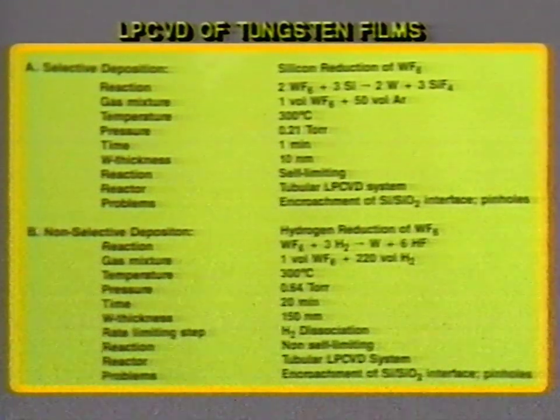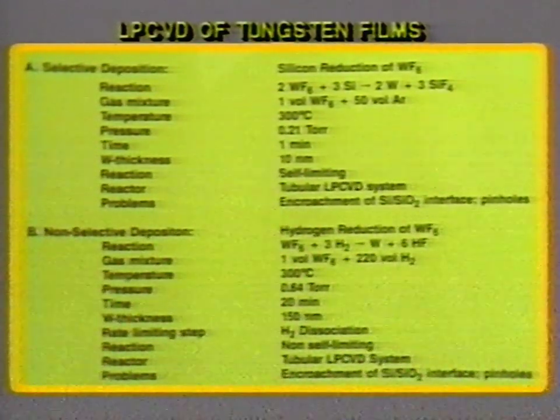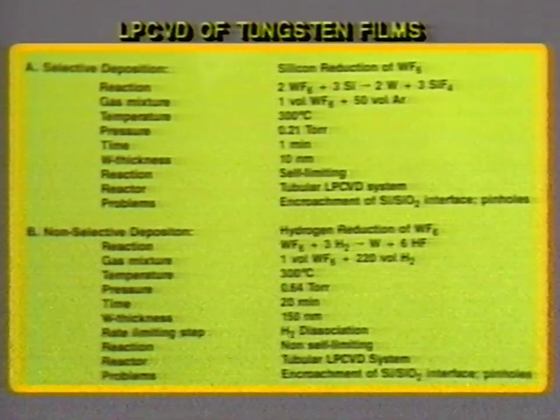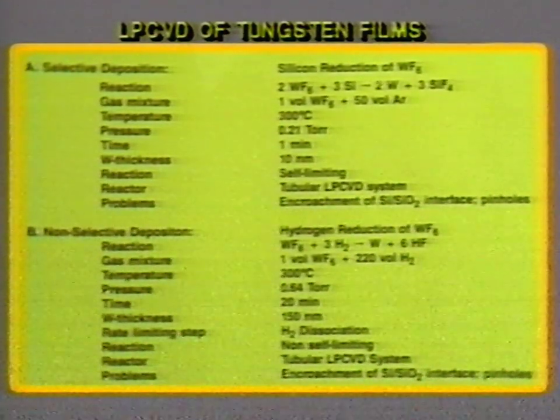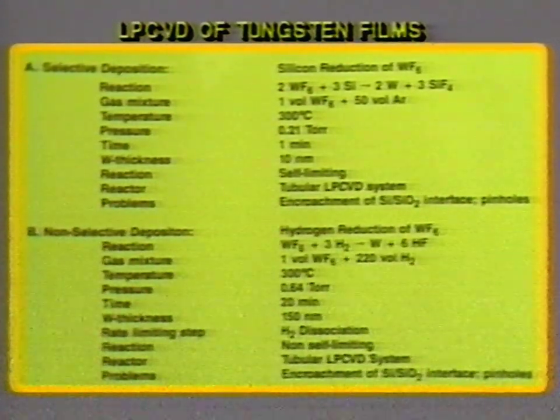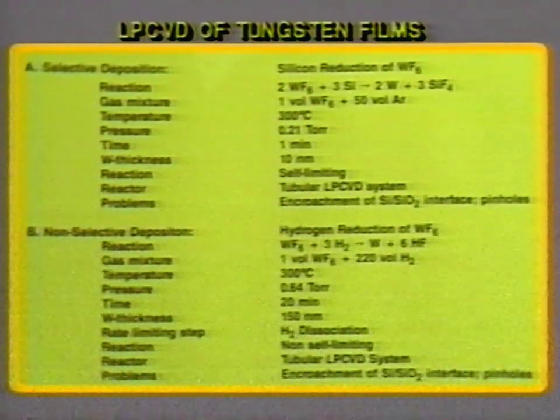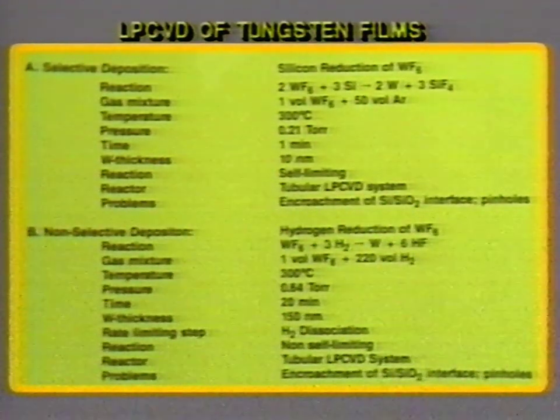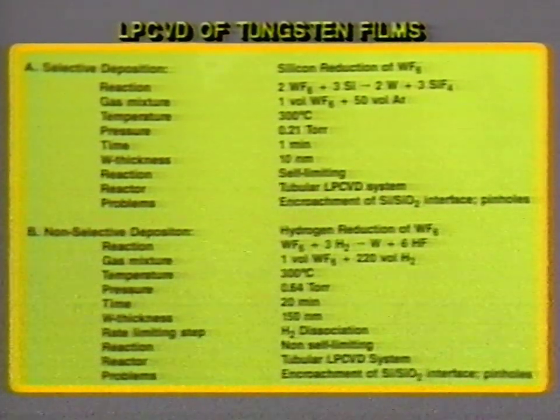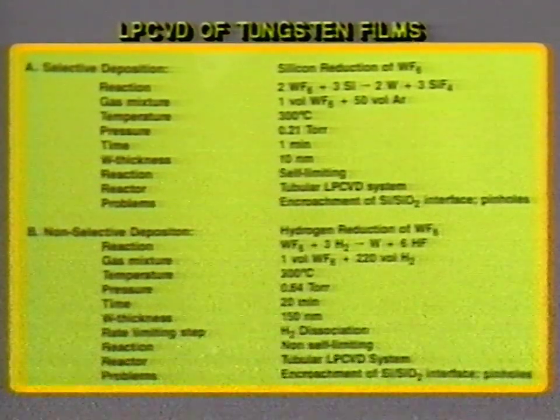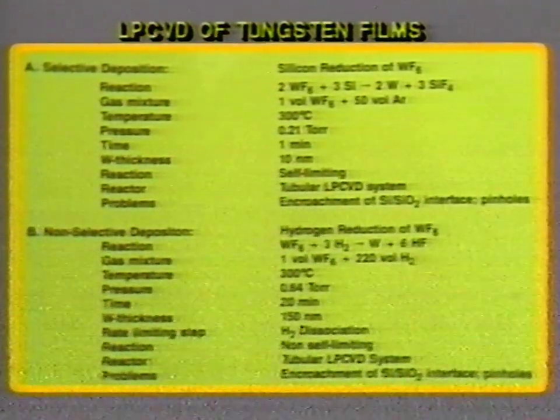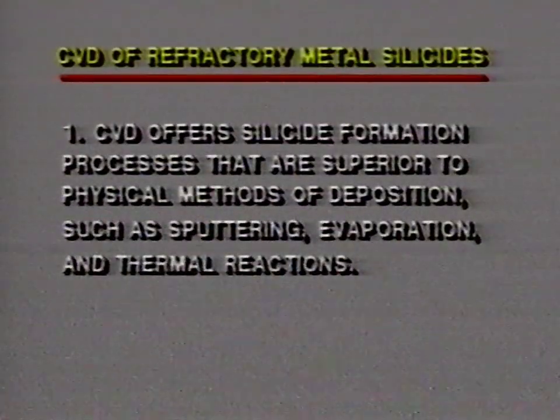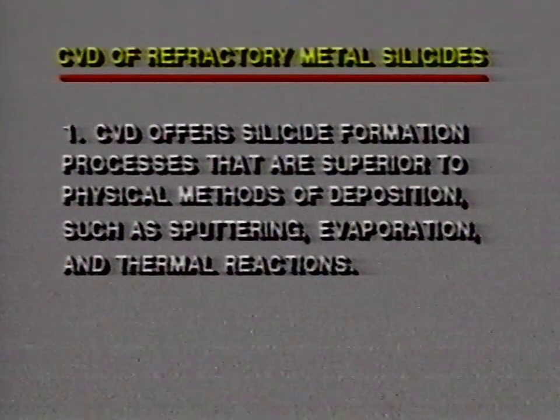In this particular case here, however, I have shown the non-selective deposition, namely when you want to cover the entire surface of the substrate, that is the SiO2 as well as the already coated via areas. And so by judicious choice of the reaction conditions, we can then produce a film that meets the requirements for high temperature intermetal metallization systems. Let me just backtrack for a moment here, and I have a summary here of the silicides.